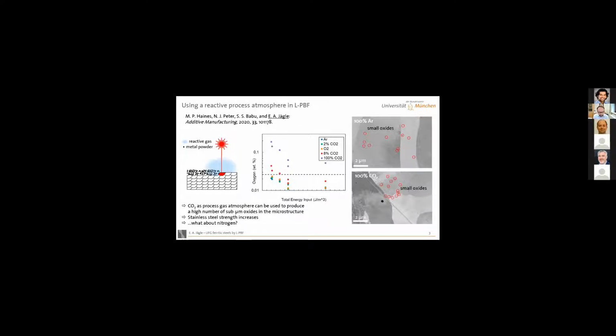Right, so that kind of worked. We also saw an increase in hot compressive strength. Unfortunately, we couldn't do creep tests, but about a 20% increase. So we were very happy about this result.